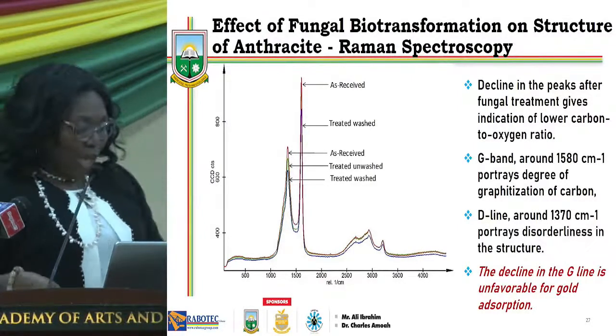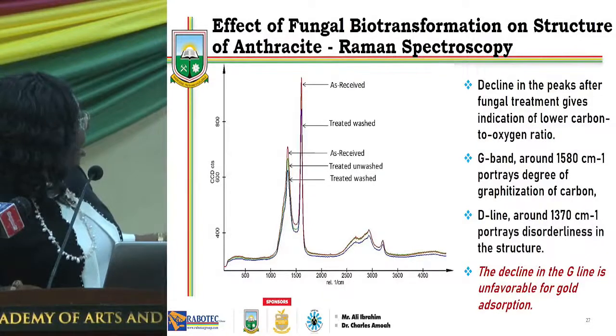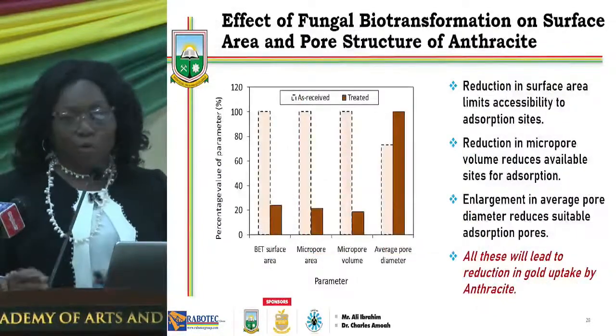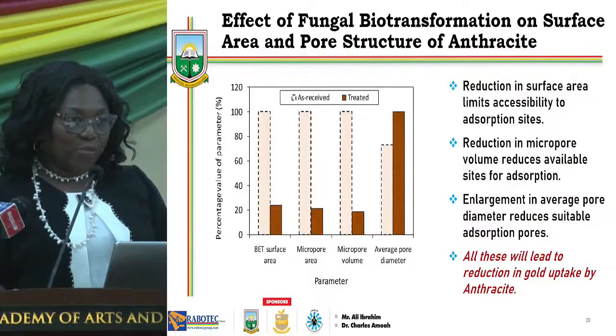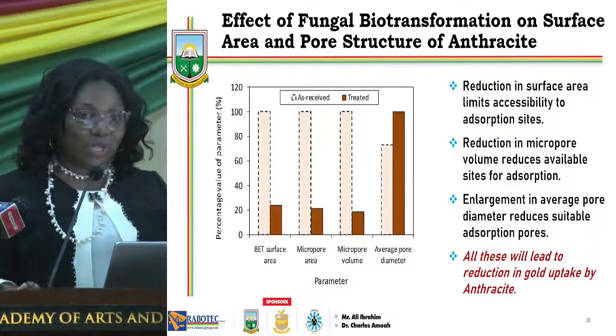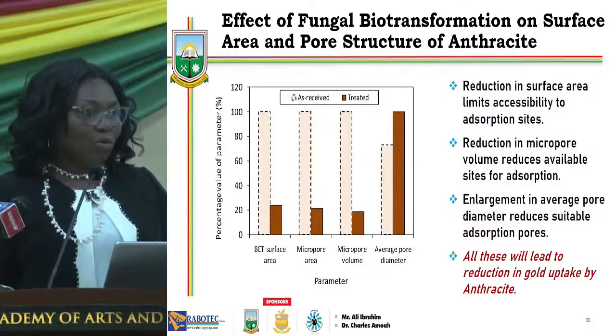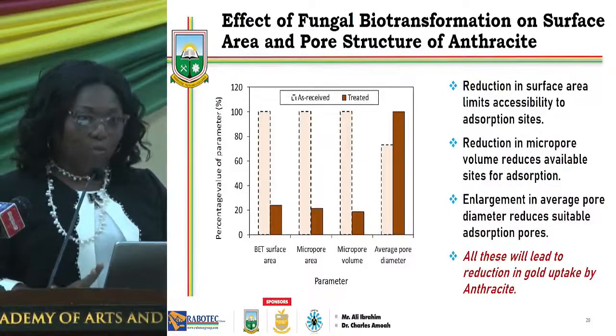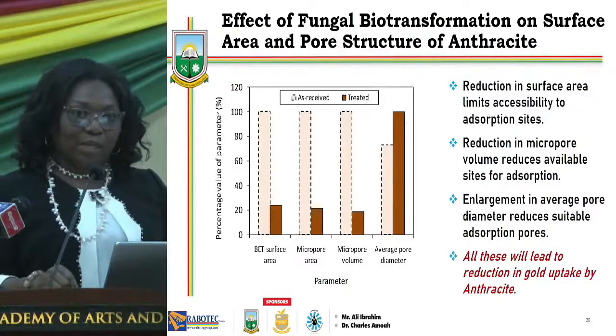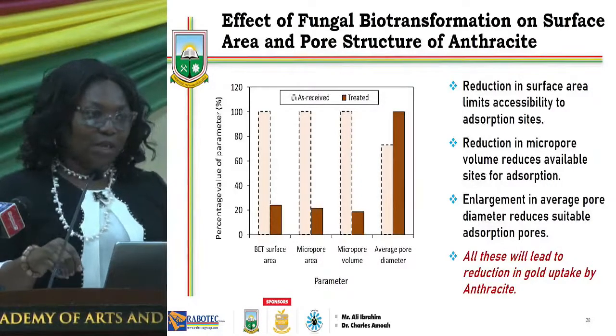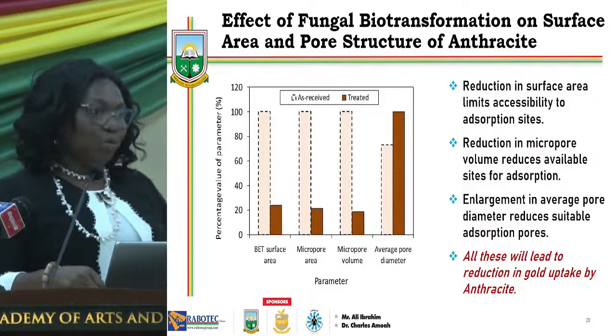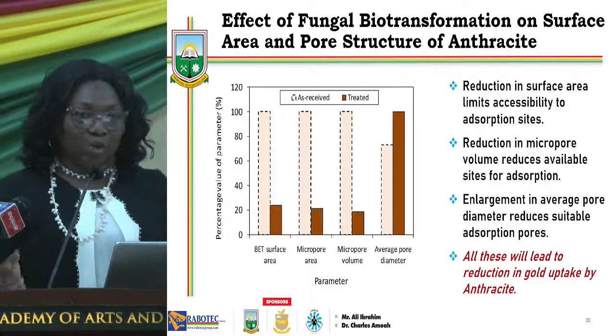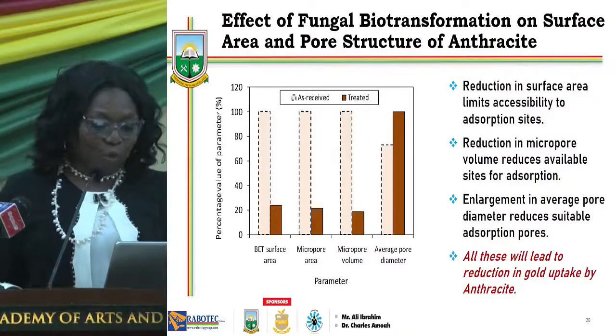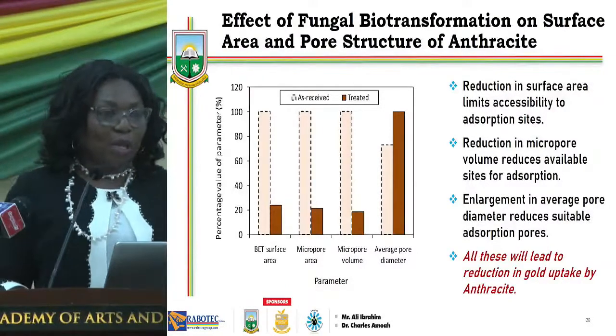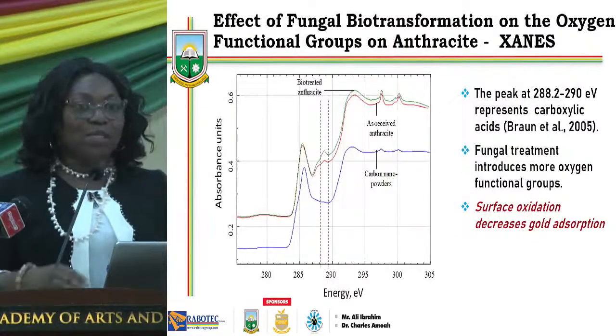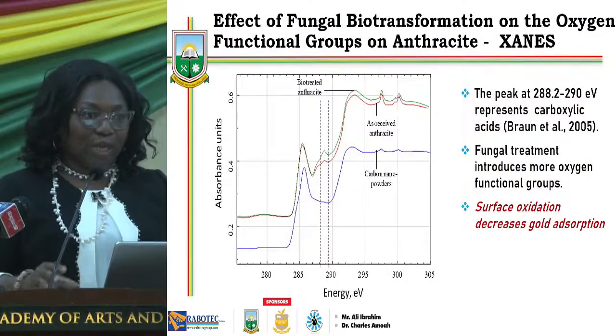The diagram here also gives us an idea of the surface area and porosity. From the treatment, the surface area of the carbon reduced, and the pore volume also reduced. The micropore structure and micropore volume reduced, whilst the bigger pores increased, and those are not good for gold absorption.